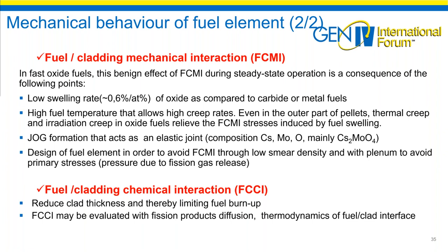Finally, the design of the fuel element contributes to avoid this mechanical interaction, with a smear density adapted to the evolution of each of the materials with the performances requested. This means that we will have to adapt the smear density depending on the burn-up you want to reach.